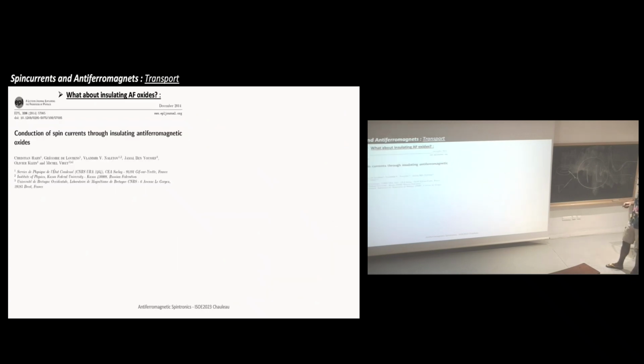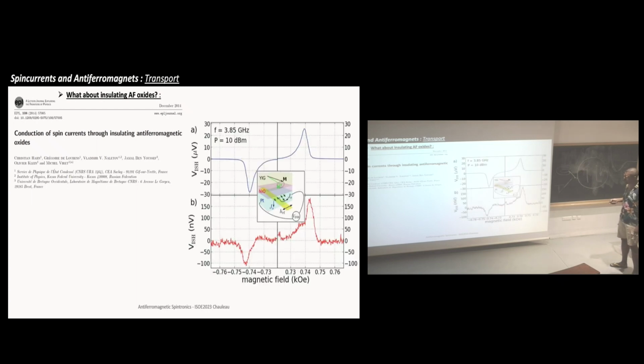So what about oxide? There have been some very nice demonstrations of conduction of spin currents through insulating antiferromagnetic oxide, and this has really triggered the field of antiferromagnetic spintronics. And the concept is the following. So you have yttrium iron garnet material, which is a ferromagnet, fair enough. Then you have NiO, which is antiferromagnet. Then you have platinum, which is going to be used to convert spin current.